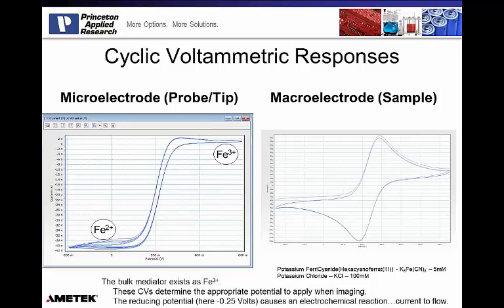So that's the reaction couple. I'm looking at iron 3 plus to iron 2 plus, and there are some different things that I'm going to take away from this sub-experiment, if you will. Primarily, this tells me what potential I'm going to use when I go to imaging of my area maps and line scans. If I have the system as designed here for this experiment, if I were to apply a positive potential or an oxidizing potential to a solution where iron already exists in the 3 plus or oxidized state, I get no electrochemistry happening at my probe. That means no current flows, and that means my scanning electrochemical microscope is not able to make a useful measurement.